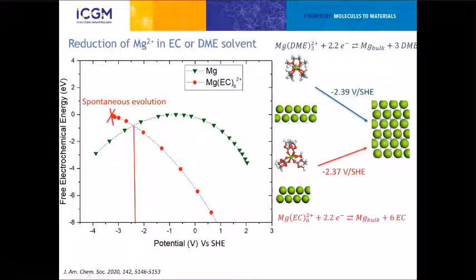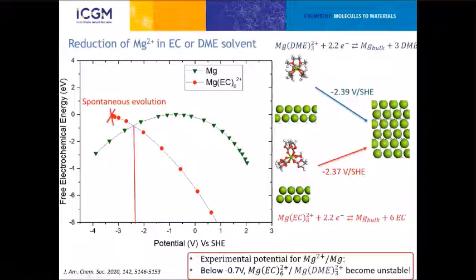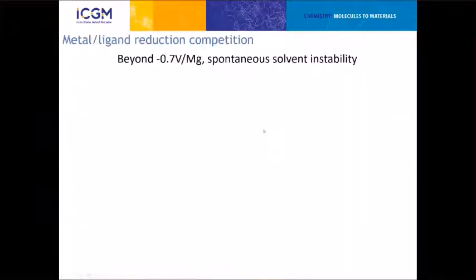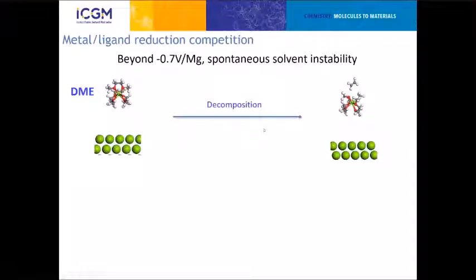When we go under too much reduction, we get some kind of instability in both systems. When we go beyond about minus 0.7 relative to the equilibrium potential, there's a spontaneous reorganization of the solvated cation that was not observed in previous studies with lithium. So it's really something specific to magnesium in this case. And what we did observe is different behavior depending on the solvent.